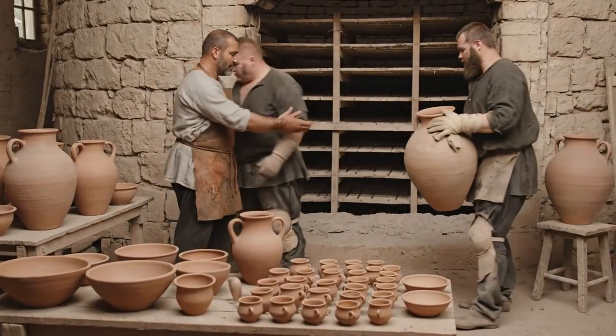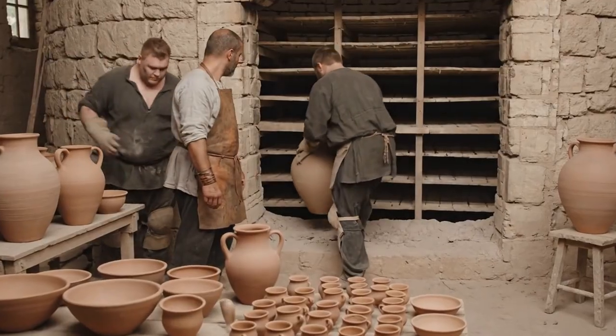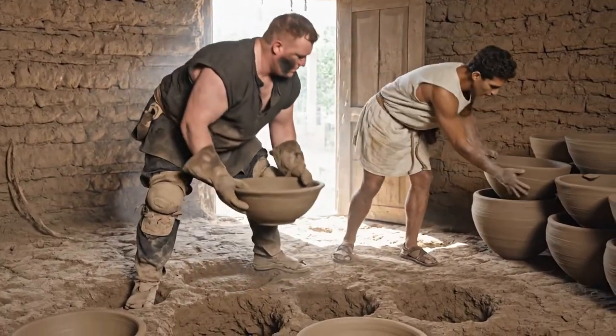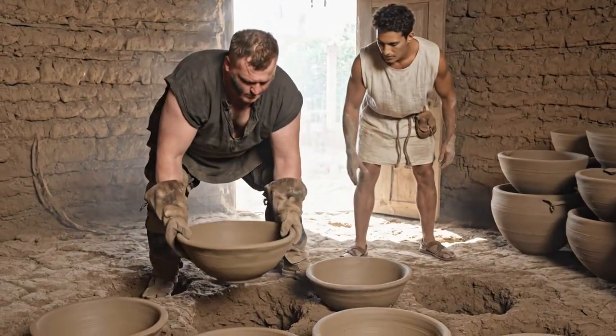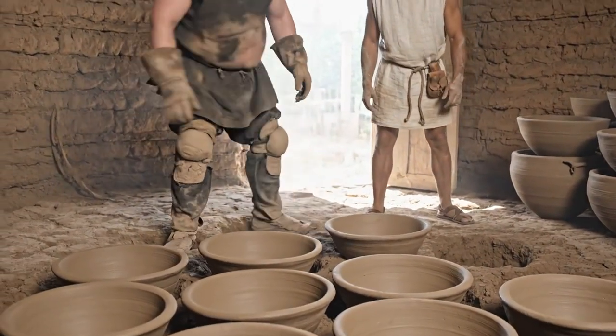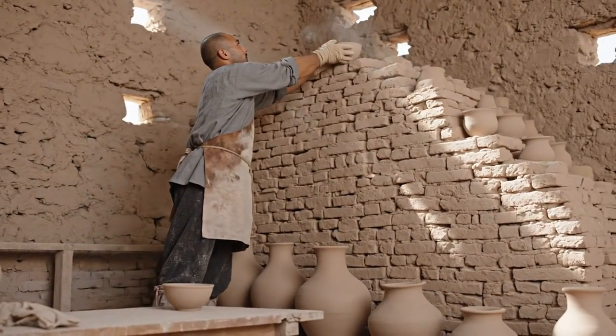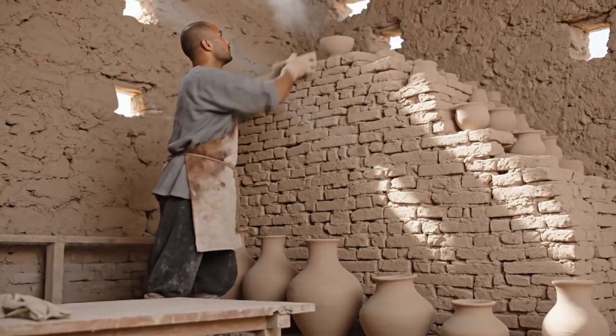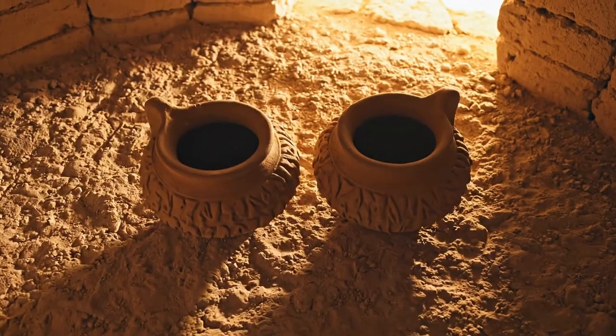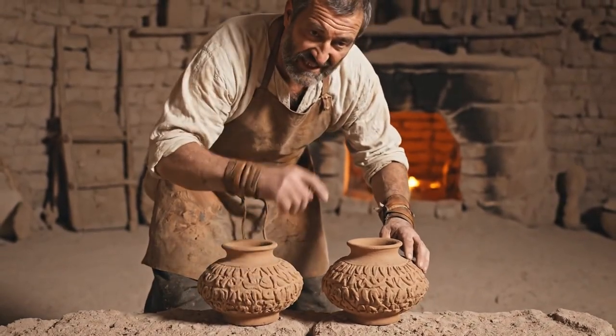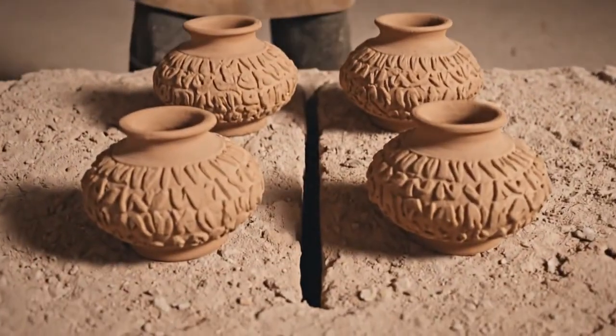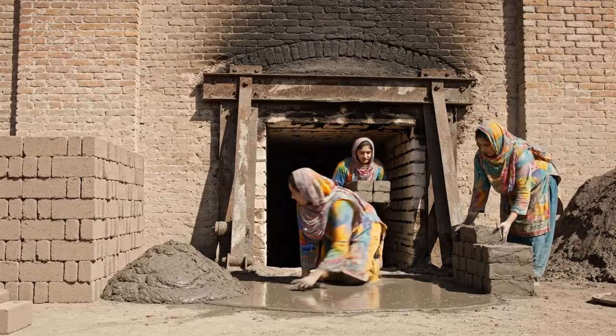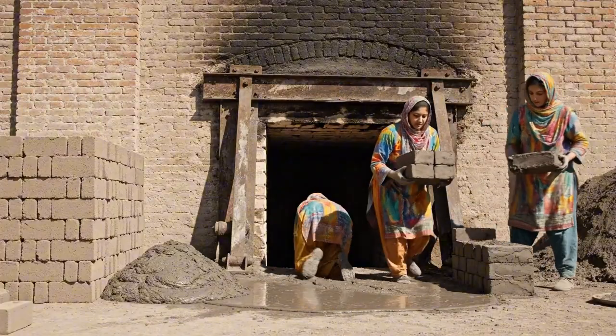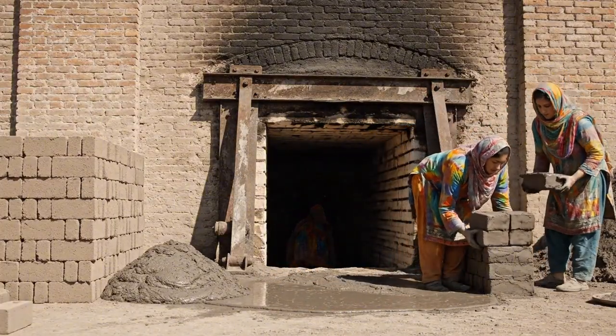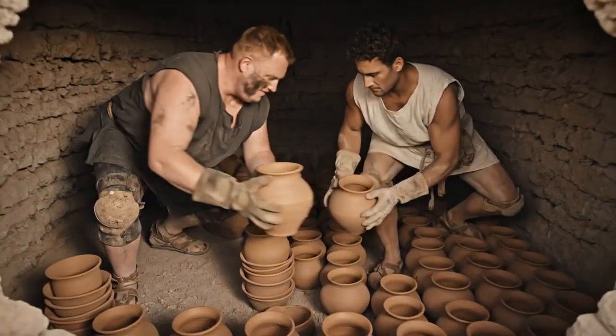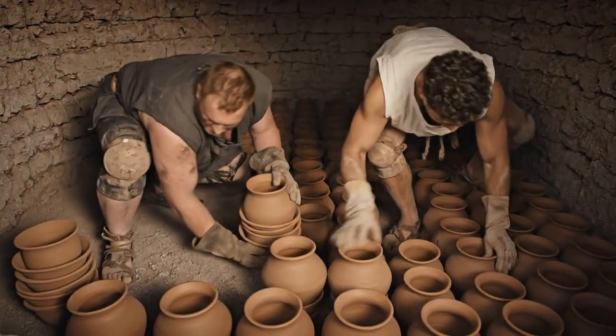Loading this kiln is a logistical operation that takes days. Each of the 9 stories must be carefully stacked with vessels arranged by size. The largest, heaviest pieces on the lower floors, where temperatures are most intense, graduating to smaller cups and dishes near the top. The vessels cannot touch one another. The sintering colloidal slip is sticky during firing, and any contact point will fuse 2 pieces permanently into a useless lump. Workers crawl through the loading door, a lateral opening in the kiln wall, sealed with small adobe bricks and a slurry of sifted earth and water once loading is complete, and arrange each vessel by hand, thousands upon thousands of them, until the chamber is full.